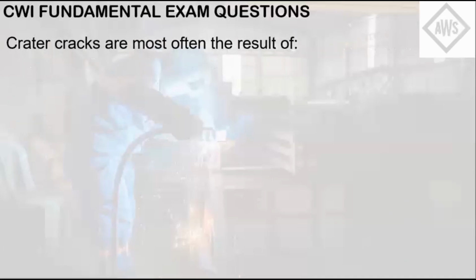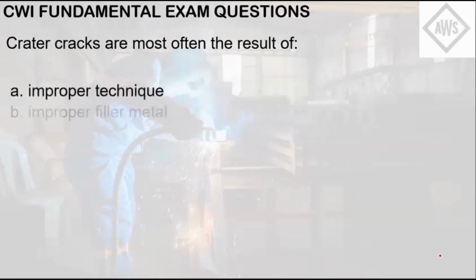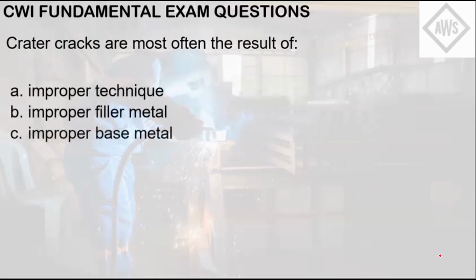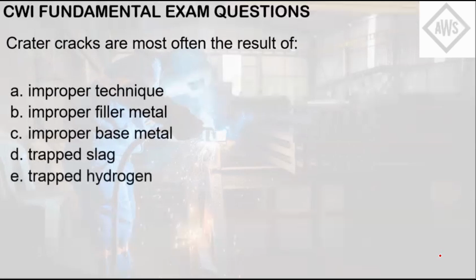Crater cracks are most often the result of letter A, improper technique, letter B, improper filler metal, letter C, improper base metal, letter D, trapped slag, letter E, trapped hydrogen. So this discontinuity is often the result of improper technique because of improper termination leading to insufficient weld metal volume and rapid cooling, causing the shrinkage in the crater area. So the crater cracks are mostly a result of the improper termination of the welding electrode in contact to the base metal, causing rapid cooling of that area, causing shrinkage.